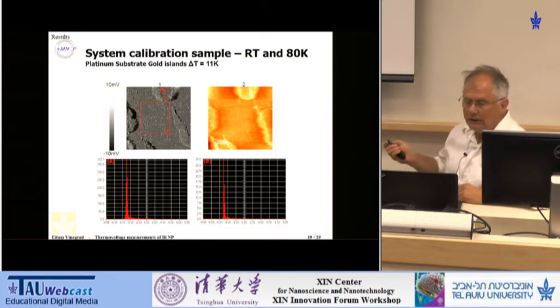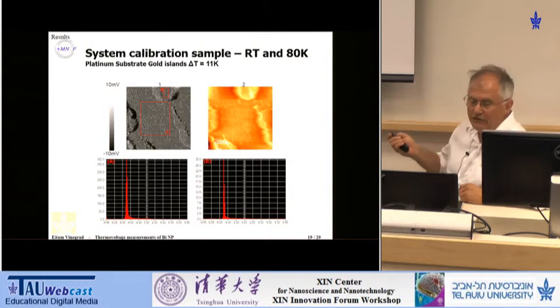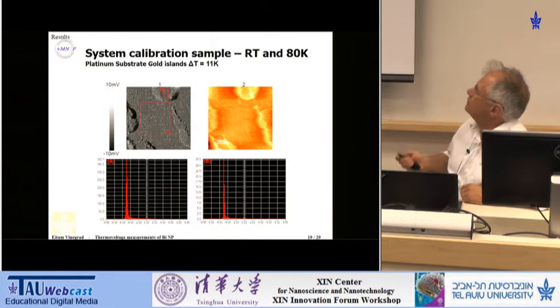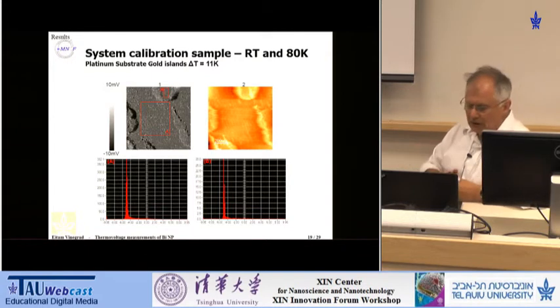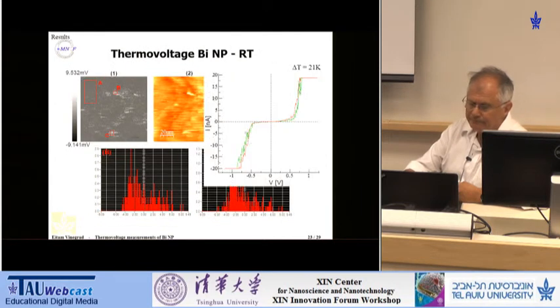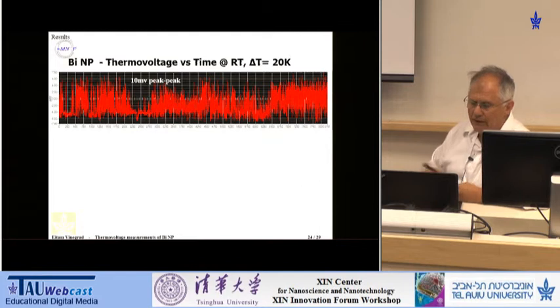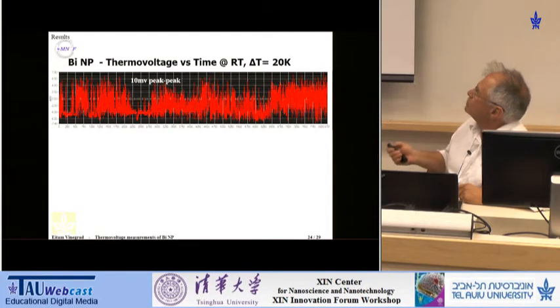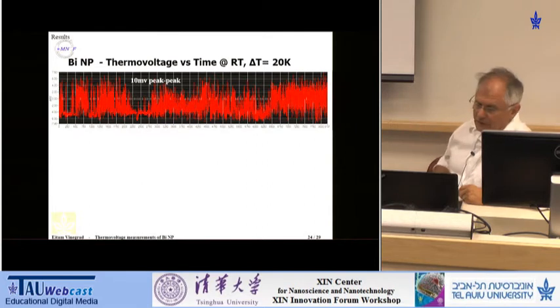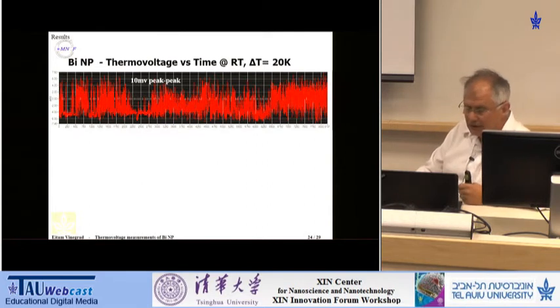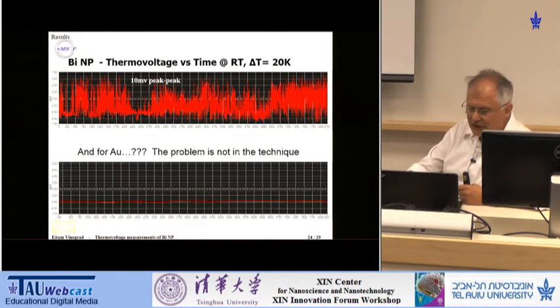platinum and gold, I think that's what you have here, platinum substrate and gold islands, then if you measure such a voltage, you have a very distinct value of thermovoltage for both surfaces, gold and platinum. However, if you do the same thing for bismuth nanoparticle at room temperature, then it's quite a hell. Then you see again very strong fluctuation. In other words, this is not a good candidate for technology. This is very chaotic particle.